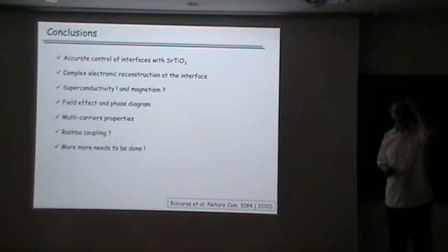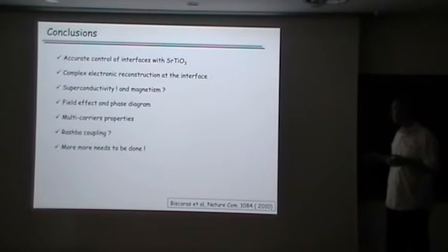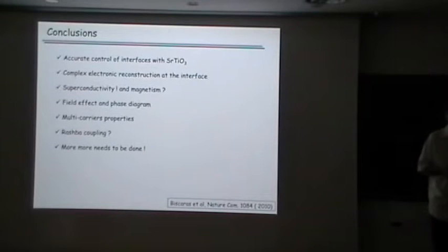Surely superconductivity is seen in the system. If we can make the system clean enough, we have a wonderful knob to tune the superfluid density and look clearly for the Kosterlitz-Thouless transition. We tried in our samples, but again, the transitions are not sharp enough right now to be sure, at least at the scale of our measurements, that we observe the Kosterlitz-Thouless transition in detail. And the magnetism question is open here.